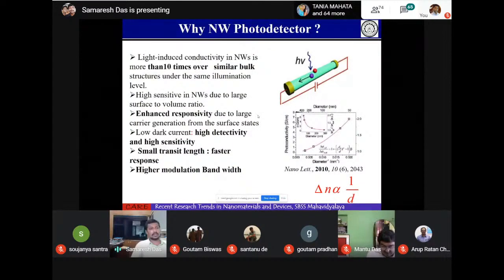You know, these nanowire photodetectors have some advantages compared to bulk photodetectors. They can get very high responsivity because these surface states create a depletion layer, and that can create the photogenerated carrier. And also because of the nanowire, the transit time is very fast, so you can make very fast photodetectors. People have reported up to 75 gigahertz for germanium nanowire photodetectors. So your transit time as well as the responsivity is fast. That's why the nanowire photodetector.